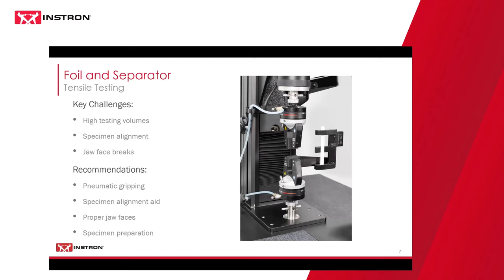So for foil and separator film, taking a look primarily at the tensile testing of these two, one of the key challenges that comes up is that high testing volume that I talked about. This is probably most prominent in foil and separator film testing. For separator film, testing is performed in multiple cutting directions. We need to make sure you can ensure quality of the material in cross-direction, machine direction, and sometimes even a diagonal direction of the material.